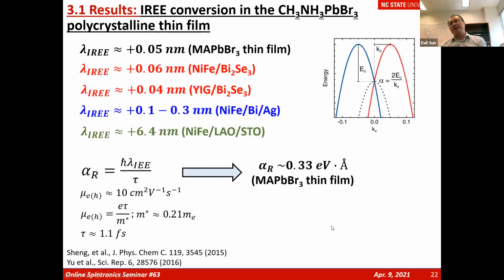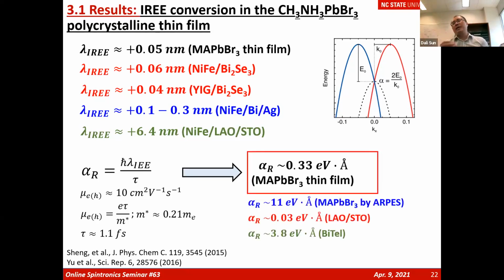Yes, we propose that what we observe is only like 0.3 eV angstroms, but that's just due to the underestimation from the whole surface. Probably the spin pumping signal we observe from a single spot, which is alpha, may be really compatible with 11 eV angstroms. But overall, it is averaged by the whole area. That's why it's reduced. How big is that red spot?